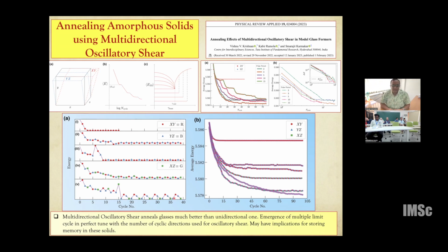Which I may come back to if I have time. These absorbing states store memories. So if you do multiple-direction oscillatory shear, there are possibilities that you may be able to store multiple memories along those directions, which is not yet achieved, but the possibility still holds. But what is most important and interesting is that with better annealing procedures, although the phase diagram remains very similar, there also you have an energy scale below which you can no longer anneal your sample using the oscillatory shear protocol. So mechanical annealing seems to have a lower bound.